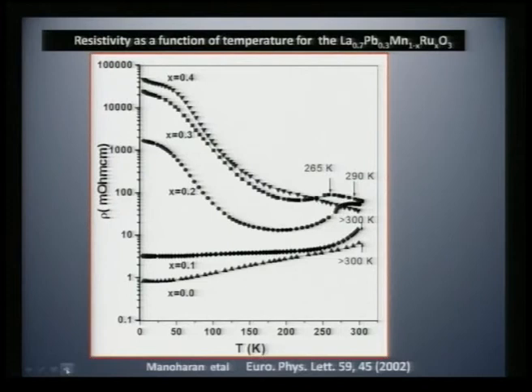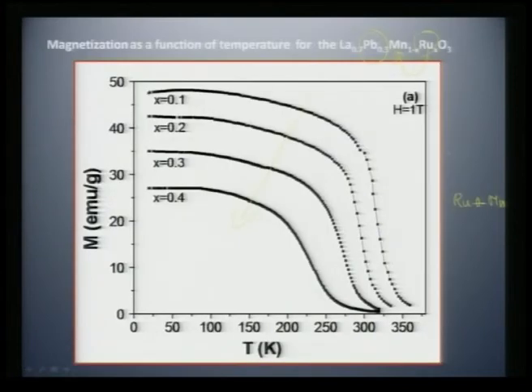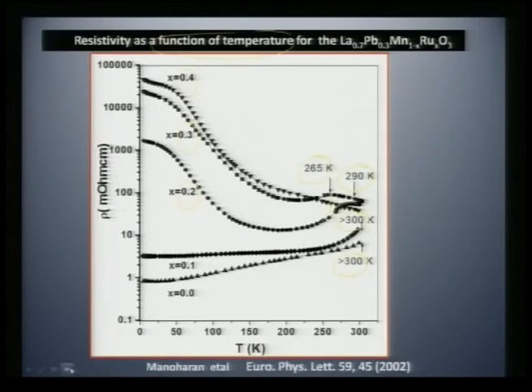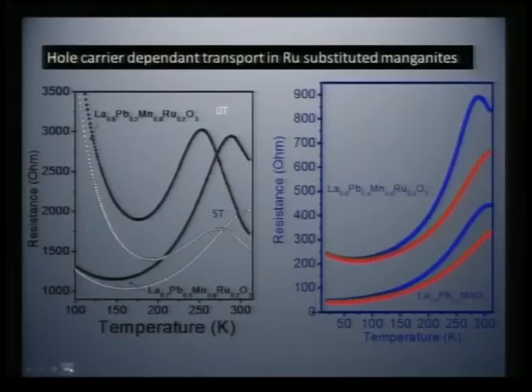This is also pronounced in the resistivity as a function of temperature plot, where you can see the parent compound is showing a clear metallic transition, whereas 10%, 20%, 30% and 40% of ruthenium still shows a clear metal insulator transition corresponding to the magnetic transition which we saw in this case. So, if you take these metal ferromagnetic transitions, and compare them in the next curve with the resistivity plot, you still see a clear correlation happening. So, something is very unusual here.